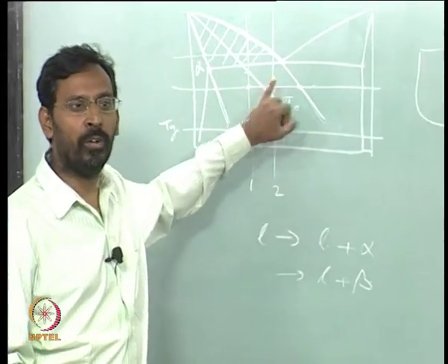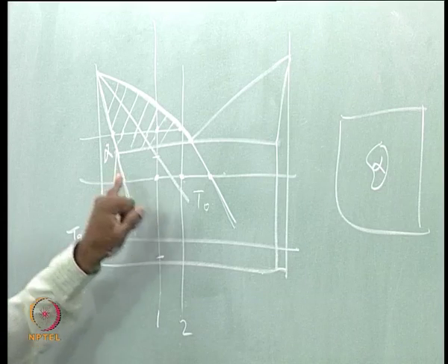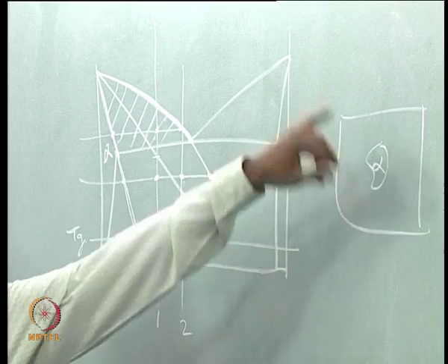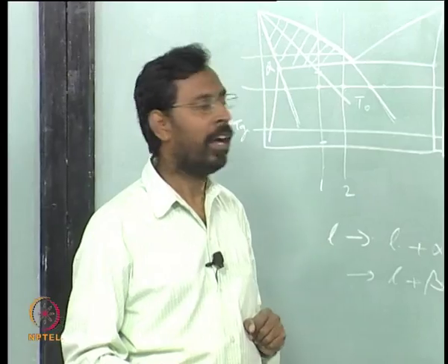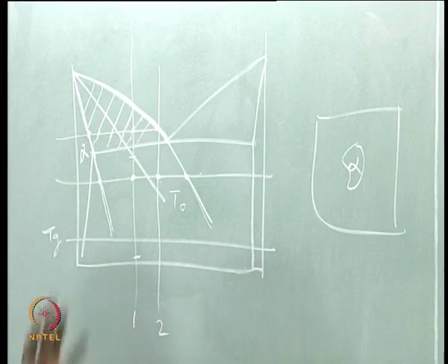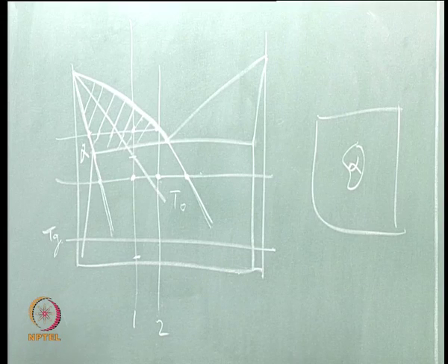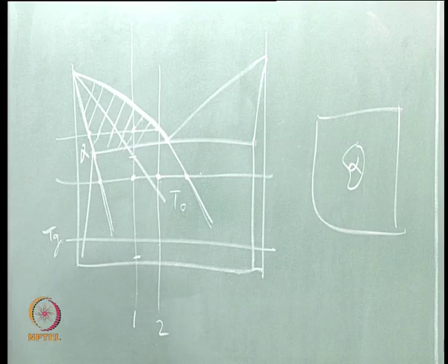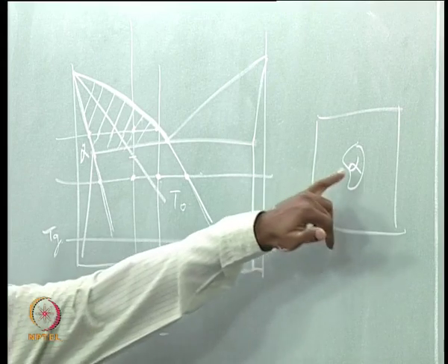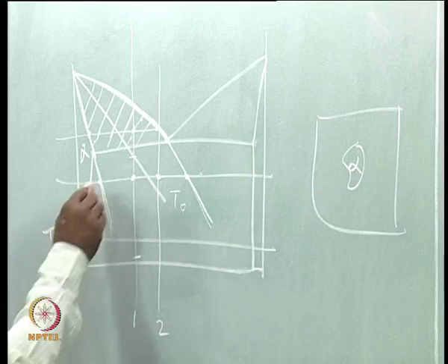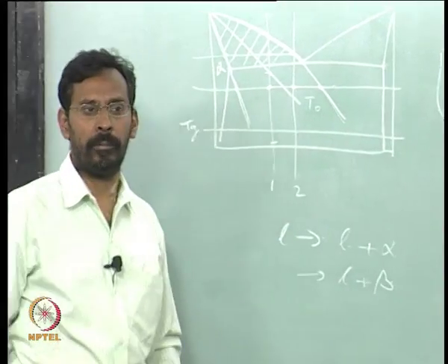So, you will see that in all these cases, though the alpha that comes out initially will be of this composition, at some stage the remaining liquid gets converted to beta. So, you will have a situation of beta matrix and an alpha phase, and as you hold for a longer time, as you cool to lower and lower temperature, this alpha slowly changes to the equilibrium composition of alpha, because the moment beta comes out, alpha of this composition cannot be in equilibrium with beta.